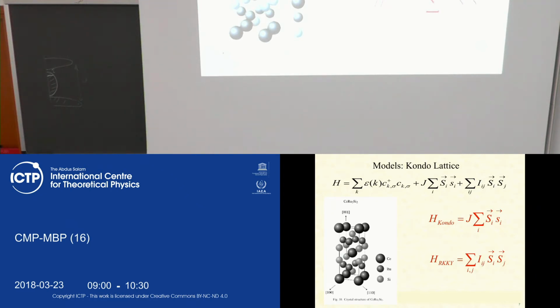This is yet another problem for which we have not yet found a solution, and the scientific community has not yet agreed about this solution. However, let me start with some theories which were developed to explain the mechanism of formation of heavy masses in cerium-based compounds. As I said, the model consists of conduction electrons, which are s-p-d electrons of the conduction band, and localized spins. Since the localized spin can interact with the spin density of the conduction electrons, it produces this term, which then leads to the Kondo effect.